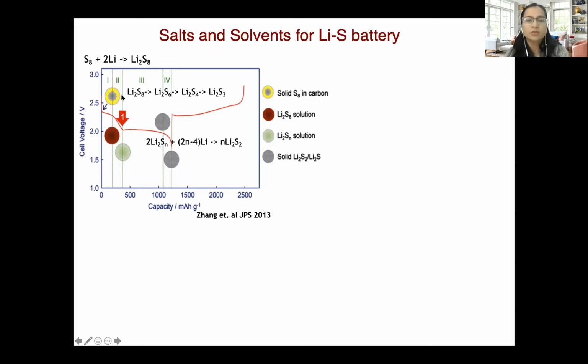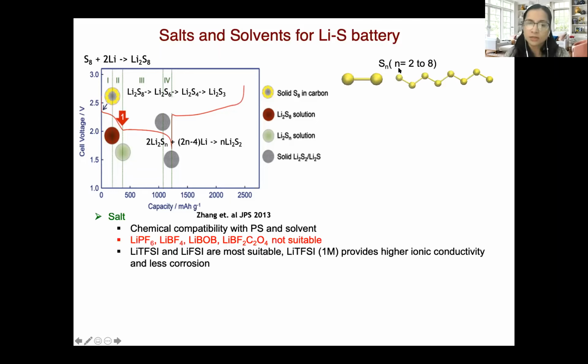Another thing to note here is that the Gibbs free energy of these different lithium polysulfide species is very close to each other. And that's why they basically coexist in the solution through a series of chemical equilibria. So in our work, we considered lithium polysulfide species all the way from Li2S2 to Li2S8.